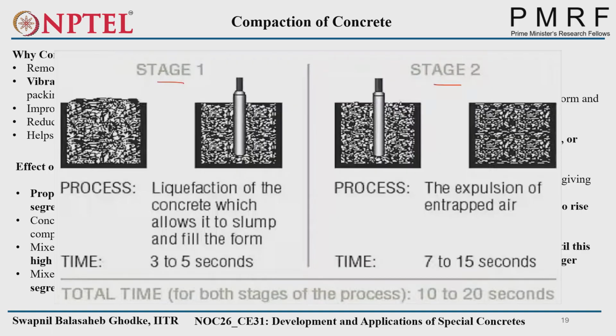This is the schematic of that one also. You can see the first 3 to 5 seconds, the liquefaction of the concrete which allows it to slump and fill the form. Next 7 to 15 seconds, the expulsion of entrapped air will happen. Then only we'll say that the compaction of concrete will complete. So total time for both the processes is about 10 to 20 seconds.